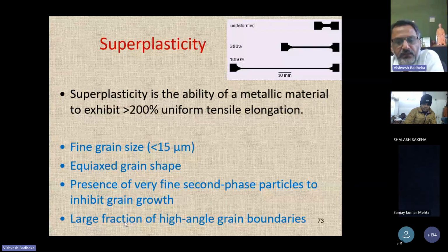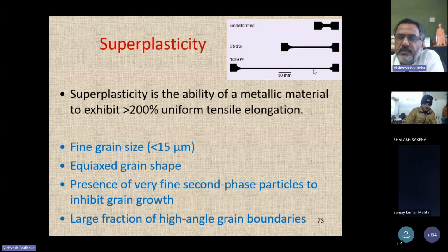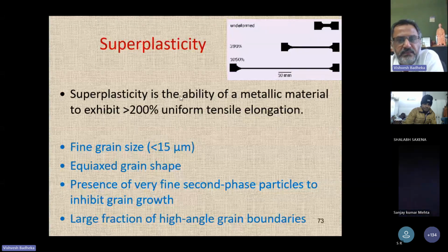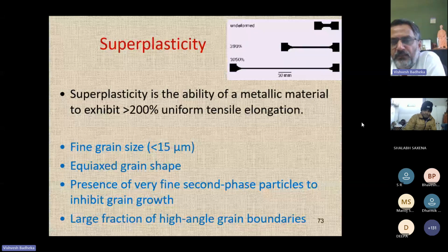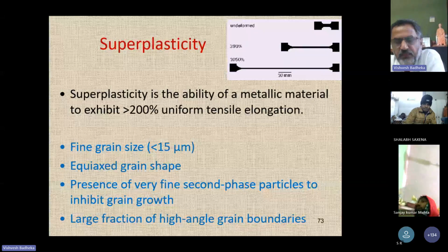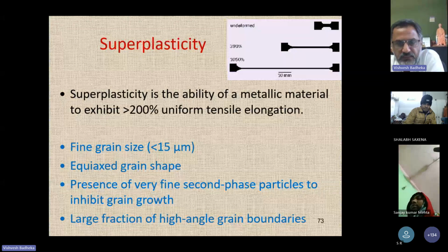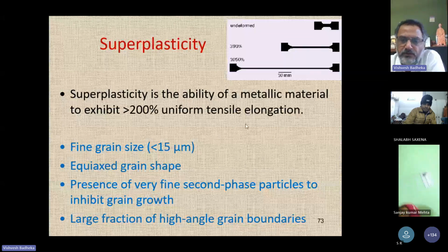And with the FSP, you get grain boundaries which will be higher angle grain boundaries. So these four attributes: reduction in the grain size of the order of less than 15 micron, equiaxed grain size, presence of fine second phase particles, and the fourth one, high angle grain boundaries. These four important factors lead to this kind of deformation, which is called superplastic behavior of the material. And this can be achieved with the help of friction stir processing. So this is another area of research wherein a lot of work is going on in that particular domain also.